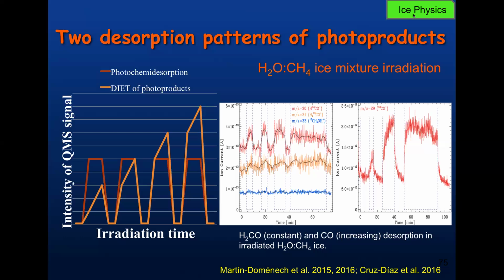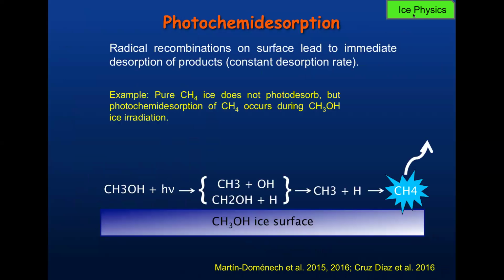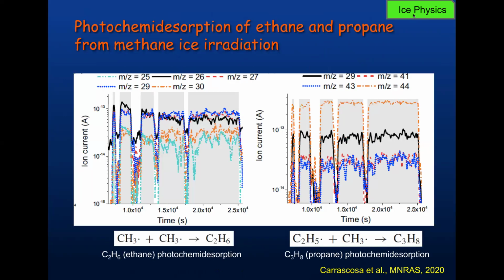And basically this is, we think, the reaction of radicals on the ice surface making a product like methane when you irradiate methanol ice, and with the excess energy of the formation, this methane on the surface will immediately desorb. This is what we call photochemical desorption. And you can also observe photochemical desorption of some complex molecules like ethane and propane in the methane irradiation experiment. So this is a way to eject large molecules from the ice so that they can be detected with radio telescopes.